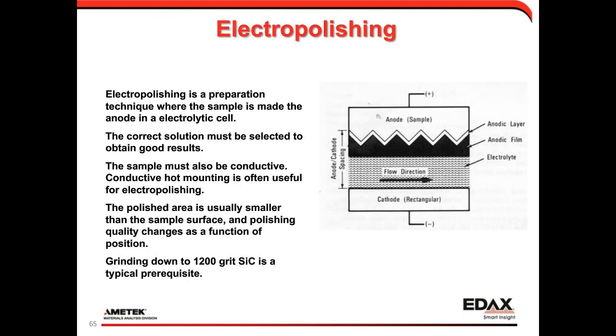So another approach we can use to prepare samples is electropolishing. That's where we take a sample and make it an anode in an electrolytic cell. To do this, we have to choose the correct solution to use. The sample also has to be conductive, and so that's where hot mounting can be useful for electropolishing.